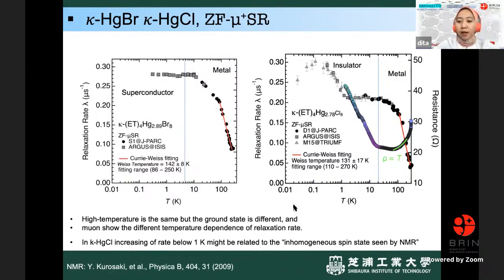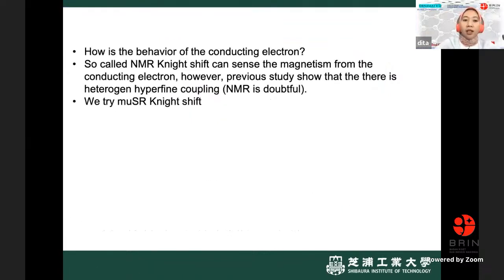You can see also this is the resistivity, the charge situation, changing from metal to insulator transition, and we see a plateau in the μSR relaxation rate. Then how is the behavior of the conducting electron? The so-called NMR Knight shift can sense the situation of the conducting electron. However, previous studies show that there is a heterogeneous hyperfine coupling, so NMR is doubtful. So we would like to try the μSR Knight shift.